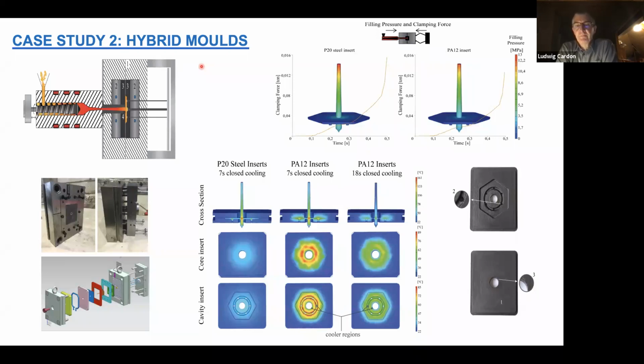So it's very fast. You have to keep in mind the difference, for instance, in crystallinity of a semi-crystalline material, depending on the speed of the cooling. Indeed, by the vapor fusion polishing principle we use together with that company, we have a rather smooth surface, but polypropylene is easy. It's possible to inject polypropylene in the PA material. Also possible is, for instance, ABS material, polyethylene, and so on. Polyamide, we also injected inside polyamide, taking in mind some surface treatments.